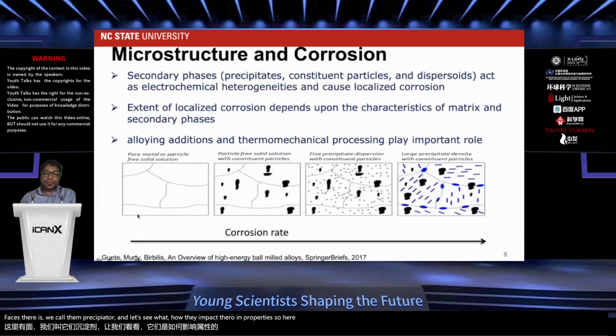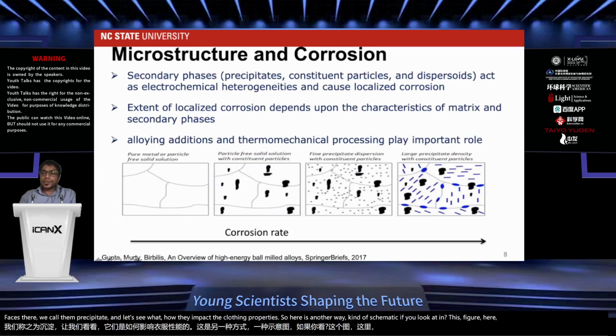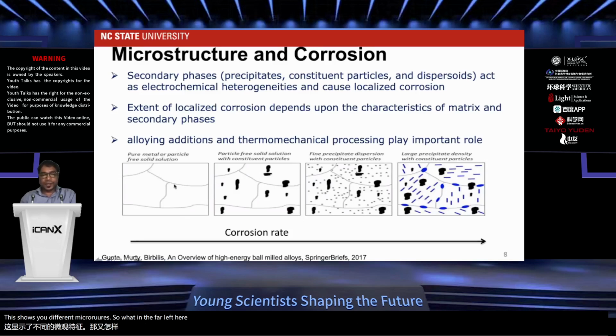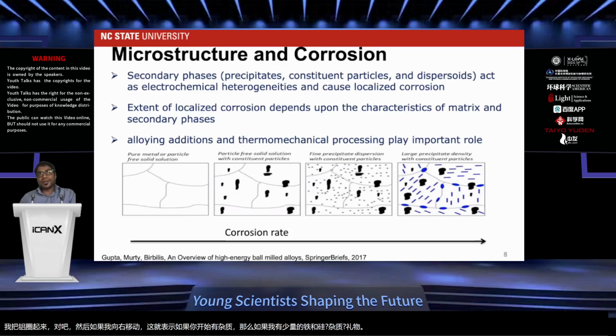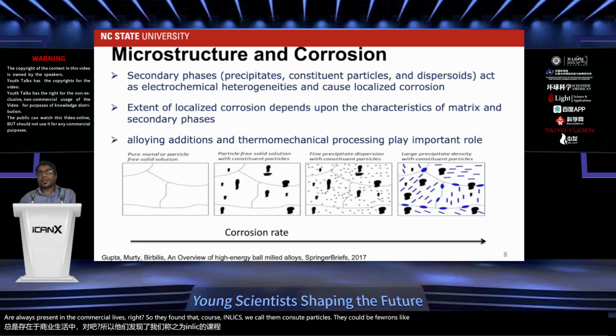So here is another schematic. If you look at this figure, it shows different microstructures. The one on the far left represents ultra pure aluminum. Then as I go towards the right, that represents if you start having impurities. A small amount of iron and silicon impurity, which are always present in commercial alloys, forms coarse intermetallics. We call them constituent particles. They could be a few microns, like 10, 20, 30 microns big, and they cause huge corrosion issues.